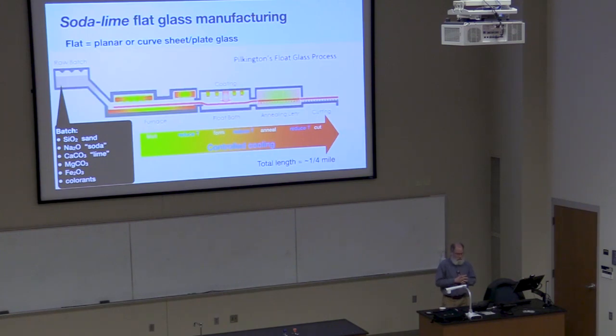So the process starts, you've got to have some batch material, so it's sand, silica sand. Sand doesn't melt very easily, so soda ash is added to mix with that silica and reduce the melting point. The problem with soda silica glass is that it dissolves in water, slowly, but it dissolves in water. So then you have to add calcium carbonate to add some durability to the glass. Magnesium carbonate's also a good material.